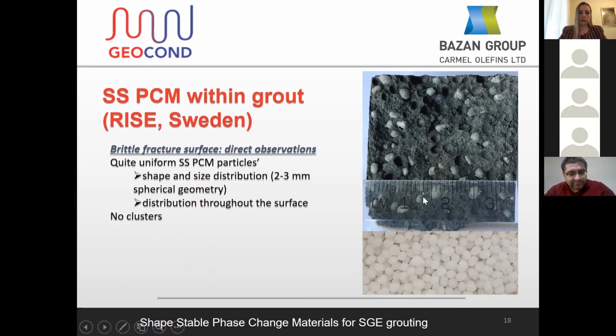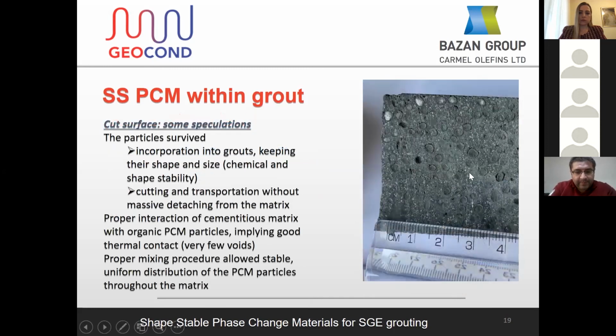And what we can see is that the shape and size of the granules of the PCM are kept. We see the granules uniformly distributed more or less throughout the grout and interacting. We see no clusters. On the cut surface of the same grout, we can see some more indications of good work done by our partners. We see the particles incorporated into the grout. We see not much detachment of the organic particle from the inorganic matrix, implying good interaction.